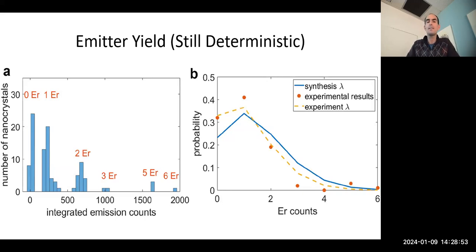The reason that is well understood is because emitters close to the surface get quenched. There are dangling bonds at the surface that basically take the energy away from the emitters. So although some nanocrystals have single erbiums inside them, there won't be any emitters associated with them. The yield is always slightly less than expected from the stoichiometry of the chemical process.